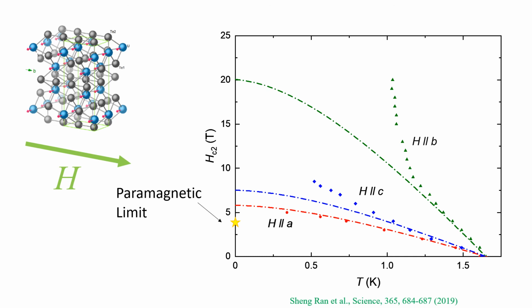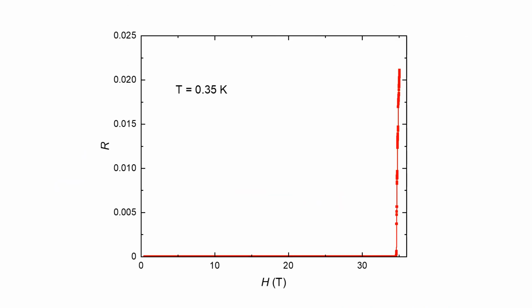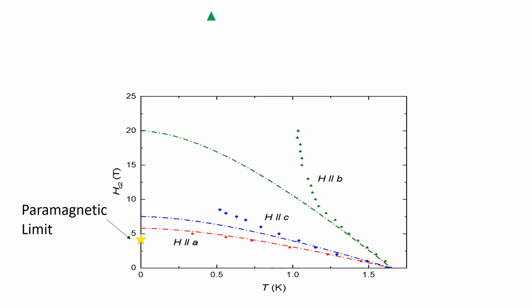In order to know how large the critical field is, we took a sample to the National High Magnetic Field Lab and measured up to higher field. Here's the resistance data as a function of magnetic field. It is 0 all the way up to 35 Tesla. And then there's a sudden increase. So the critical field is 35 Tesla at 0.35 K. Now, if we put it on the same plot, it is here, and the paramagnetic limit is only 3 Tesla. So it's 10 times higher than the paramagnetic limit.